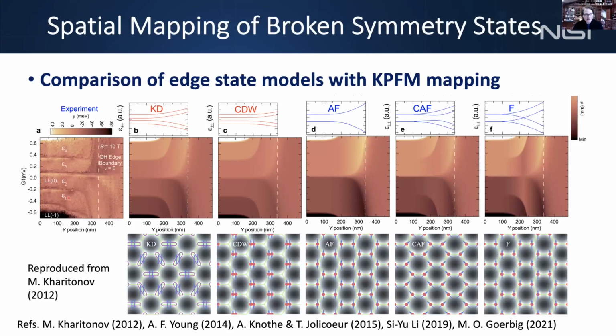Now, if we look at the energy scales here, we see that it's fully gapped from the bulk into the boundary region. So we can kind of cross off this ferromagnetic case. We don't see any gapless edge mode as you see in resistance measurements. We can't really pin down a ground state configuration from this measurement. You need more information, like on the symmetry of the wave functions. And some of that has been done already by this group, by Lee, who has shown some evidence for a Kekulé ground state. So there's more work to be done, where we really need to combine STS wave function mapping with the KPFM measurements to fully characterize these edge states.